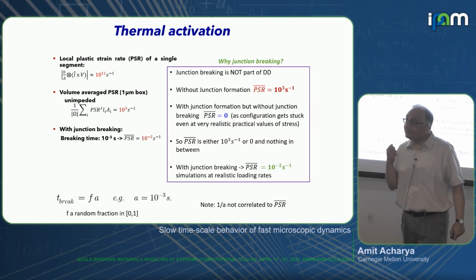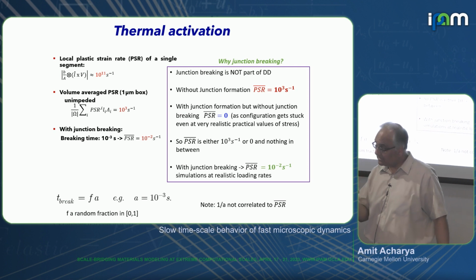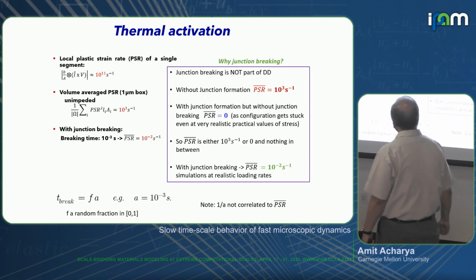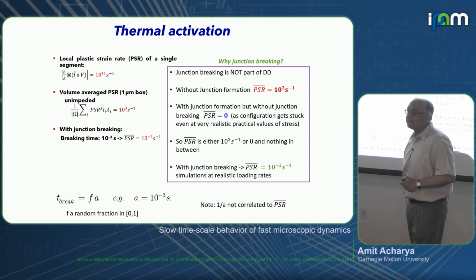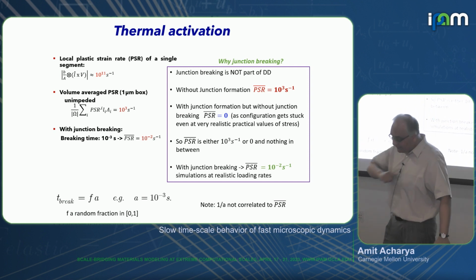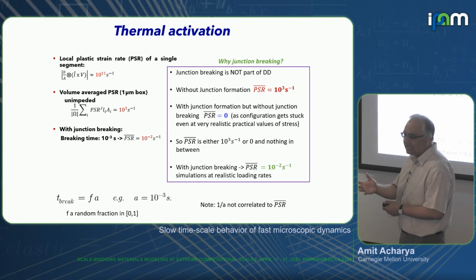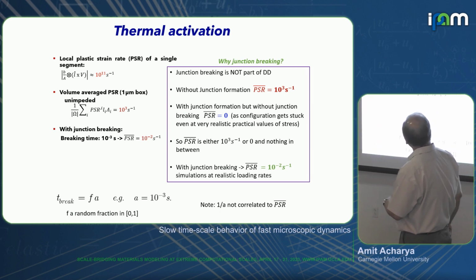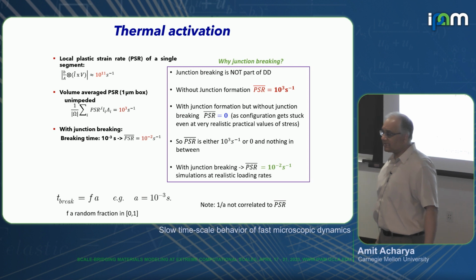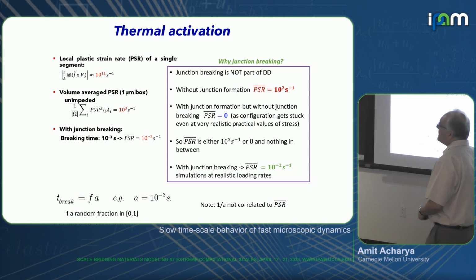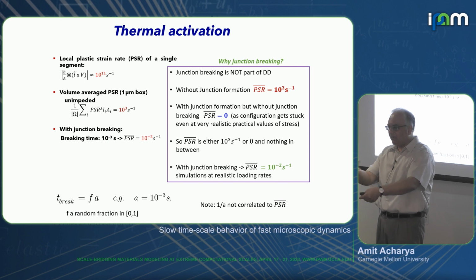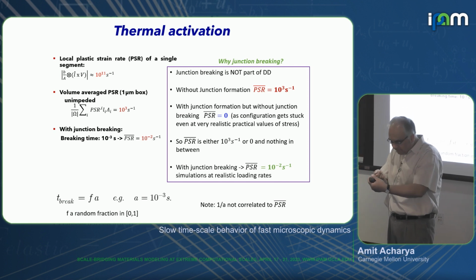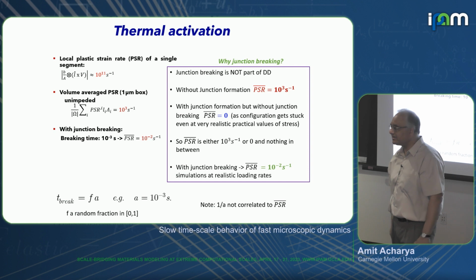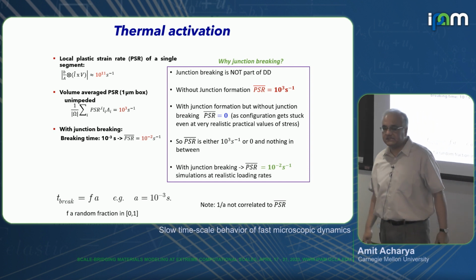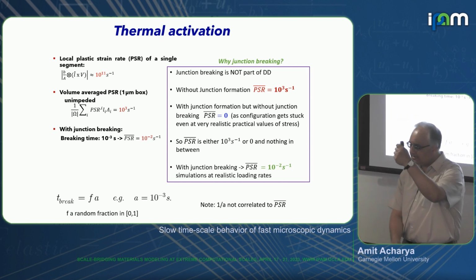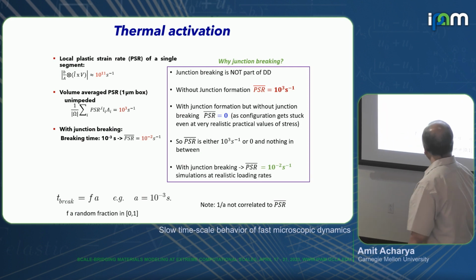And one thing we had to resolve, and this was another thing with DD, is something where microscopic stuff can really help. So if you take a box and you see free flight of dislocations, you do a little calculation: for a 1 micron cube box, the strain rate will come out to be 10 to the power 11 per second, free flight, okay? You average that over the whole box, meaning plastic strain rate is happening only along the segments. You average it over the 1 micron cube and it comes down to 10 to the power 3 per second. This is also not slow enough. This is not 10 to the minus 3 per second, okay?